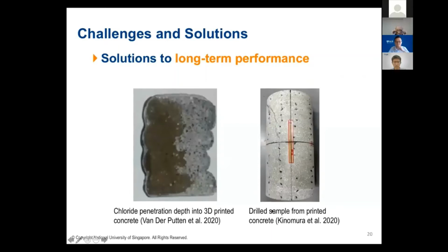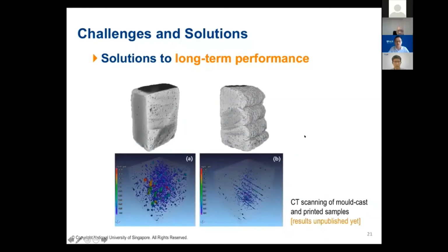This is one field sample from the printed concrete from a Japanese research group. You will find that there are lots of voids in the concrete after printing. This is due to the printing process, unavoidable or very hard to avoid. So one of my PhD students is trying to link the long-term performance with the internal structures. This is the CT scanning at the bottom, particularly the figure B. It shows the very unique pore structure or the void distribution in the 3D printed concrete. The pore has a very strong direction dependent distribution. This is along the printing direction. So any moisture, chloride, carbon dioxide can migrate.